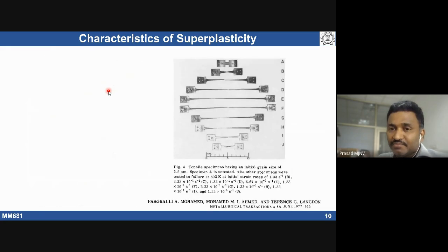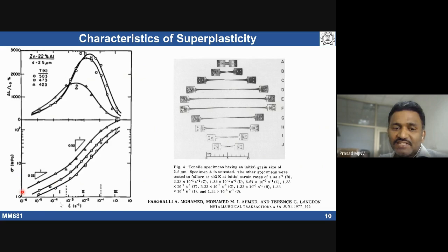If I take a zinc aluminum alloy, when it was deformed at different strain rates, at a particular strain rate the material is going to show maximum tensile ductility. So one can establish this kind of curve, stress versus strain rate, we get a sigmoidal shape. And if you measure the ductility as a function of strain rate, we get a bell shape.